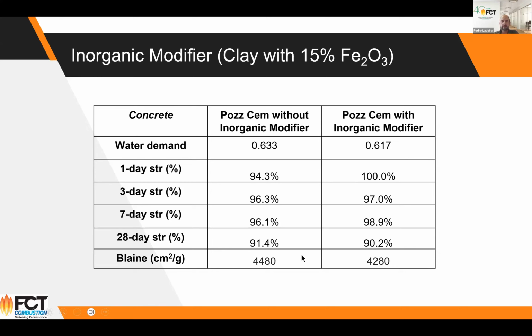The other thing that we saw is that the blaine that you achieve is lower, which means the clay becomes a bit coarser when you add inorganic modifiers compared to the clay calcined without inorganic modifiers. By being coarser, the cement gets coarser and the water demand reduces. And this is very, very important. Actually, this is key for the performance of concrete. Whenever we're moving from ordinary cement to LC3, what we see is an increase in the demand of water. And by using inorganic modifiers, you reduce this water demand. So it somehow helps you not only in the mortar but also in the concrete.